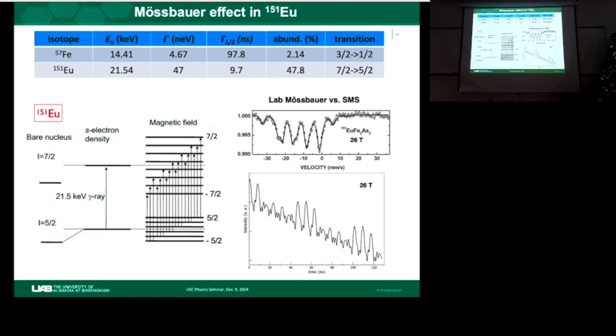57 and also europium 151. And this is the different resonant energy, the excitation energy, length, and lifetime, abundance. So europium is really favorable because this specific isotope is naturally very abundant. So we don't need to artificially enrich the sample. We just take a europium-containing compound and take data directly. But a lot of the time using iron-57, you do need to consider artificially enriching the sample so you have a higher interaction.